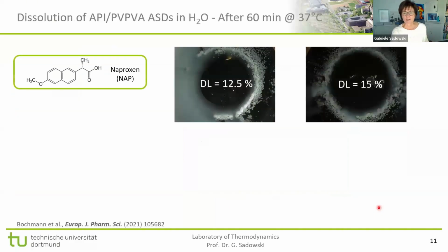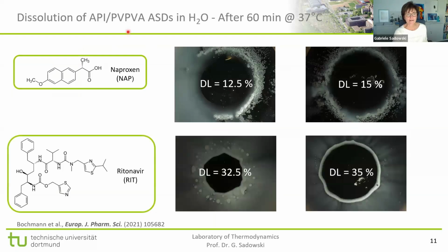This was also observed by other people for other systems. This is again the same polymer. I said this is quite often used. And these are two different molecules. And what you can see is for molecules like naproxen, which is a fast crystallizer, you see really that you have some kind of crispy shell formed depending on drug load. And you can imagine once you have the crystals here, whatever you have inside will never get released, and so it's more or less done.